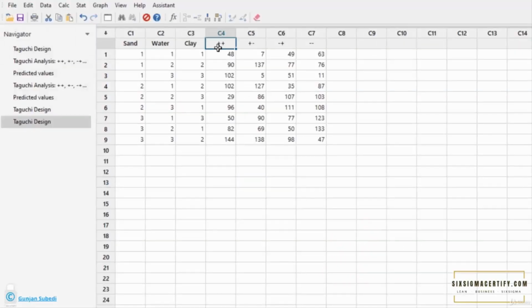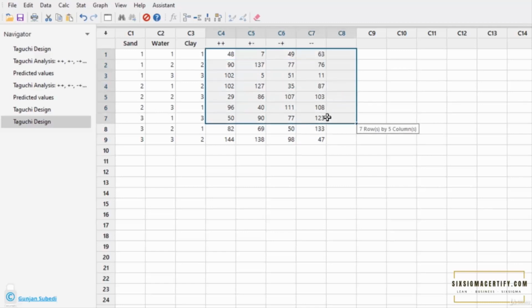At the first condition, both the noise factors were taken into consideration. The second experiment, given in column C5, was conducted in the condition where the temperature was high but the time of treatment was low. Similarly, C6 means the temperature was low but the time of heat treatment was high. In the C7 column, the uncontrollable factors or noise factors are set in such a condition that both time and temperature of the heat treatment are low. So these are the results of the compressive strength. These are all the experimental results after doing the final experiment.